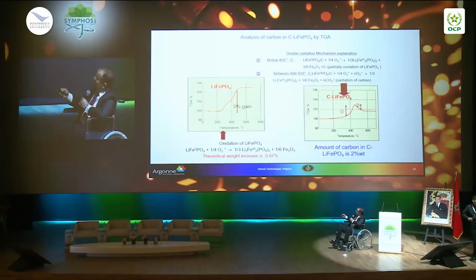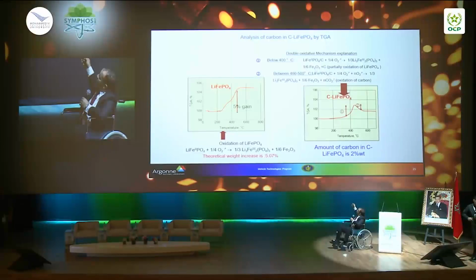To understand how much carbon we put in with the cracking, you can just use a TGA. It's very simple. If you heat up the iron phosphate, you oxidize it, you form this phase, which is a trivalent iron, and the associated weight gain is theoretically 5%. Now, if you have carbon there, once you do the same thing, you increase the weight, and once you start burning carbon, you drop the weight, and the difference is the amount of carbon that you have in your material. In this case, we have about 2%.